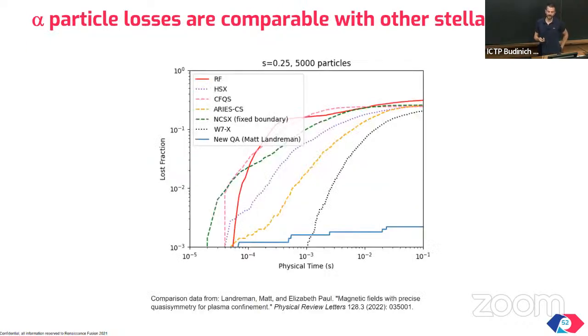Alpha particle losses. The alphas that we produce in the deuterium reaction, we want them to stay in the plasma. So the idea is 80% of the energy goes in the neutrons. We capture the neutrons. They are obviously not subject to the magnetic field, not confined by the magnetic field. The alphas are confined by the magnetic fields. And that's good because it means 20% of the fusion energy stays in the plasma and keeps it hot for more reactions to take place.